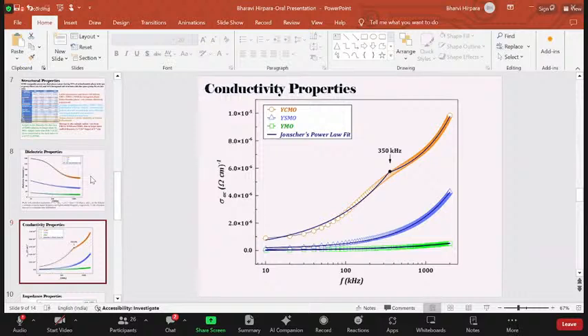Also, larger values of AC conductivity are seen for YSMO as compared to YCMO compound, which can be ascribed to the lower size disorder that supports better charge conduction across the manganite lattices. Also, here we have fitted Jonscher's power law for the material. Sorry, the equation was left out: sigma AC is equal to sigma DC plus A omega to the power n, where A is the prefactor of the system and n is the power exponent. From the Jonscher's power law fittings, we can say that the YMO and YSMO compounds experience a single nature of charge conduction through the frequency range, which can be ascribed to single nature charge conduction across the single phase lattices.